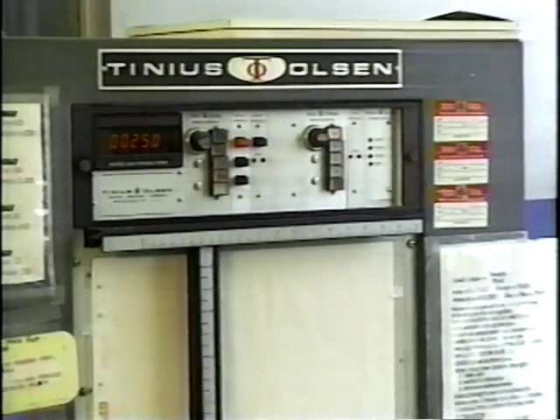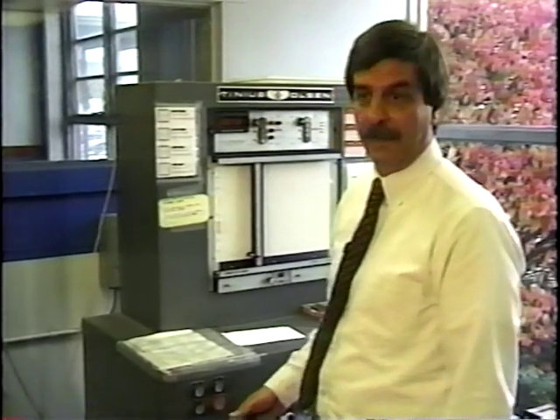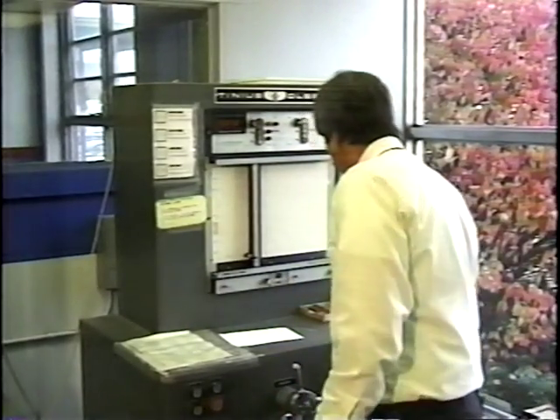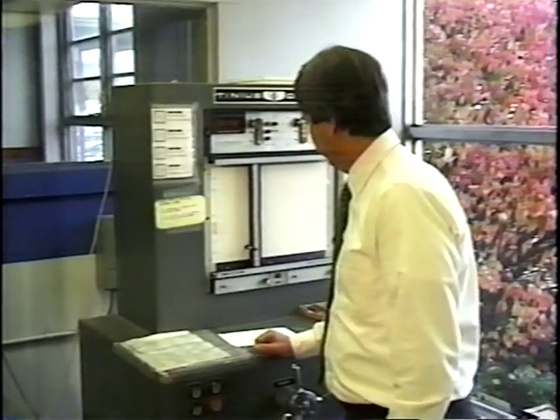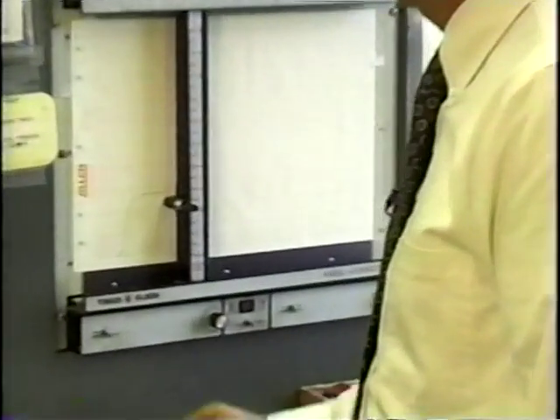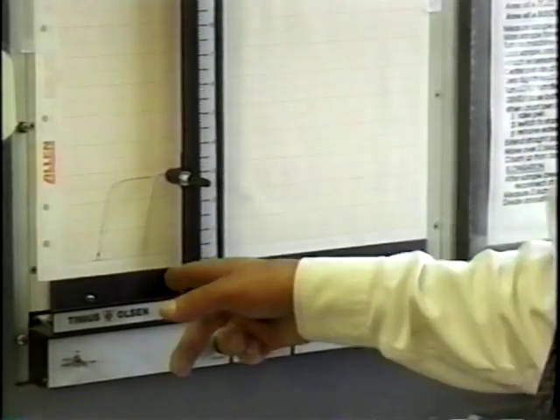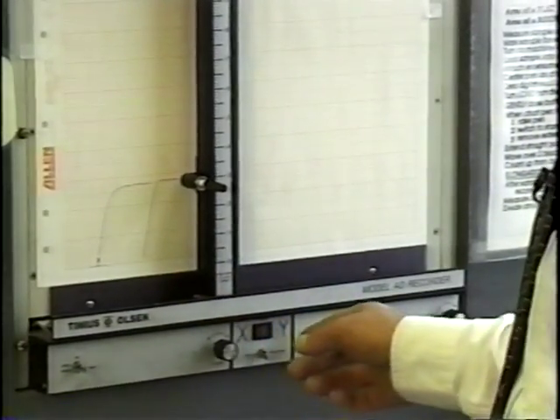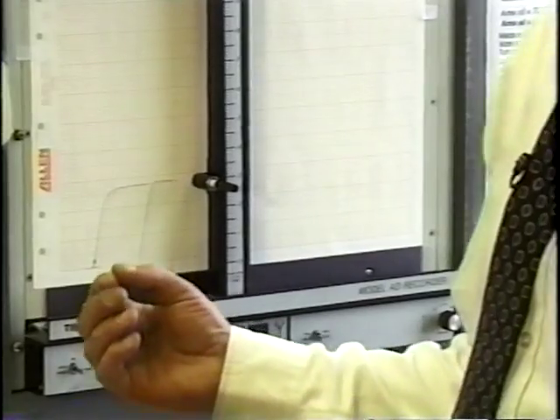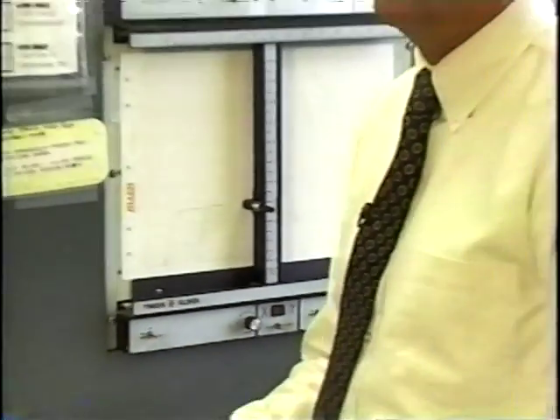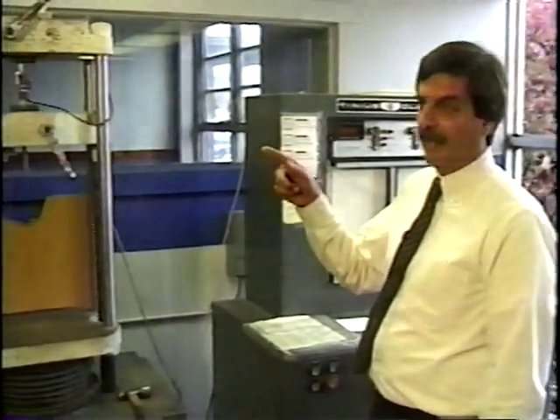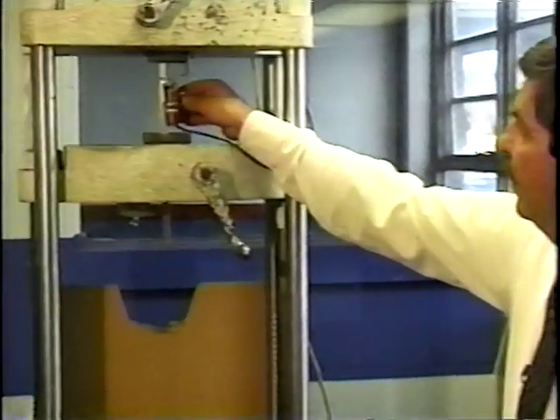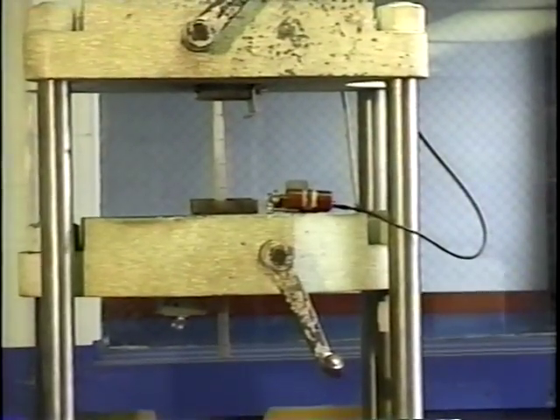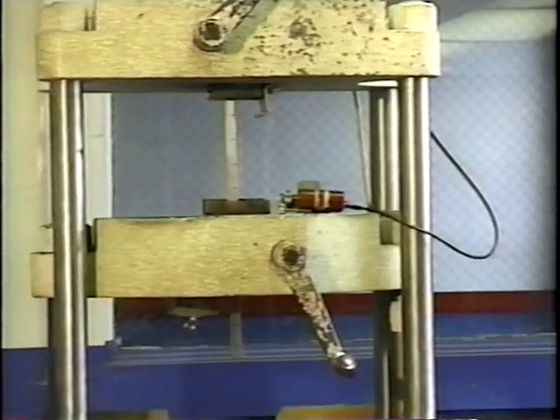Okay, one of the tests that we perform is a tensile test. That determines how strong the material is, when it's going to fail. It's very important to our customers that they know that. What we're doing here is we're plotting the yield strength. It's a stress strain curve, and it's going to tell us when the material reaches a point in its deformation and it won't go back to its original shape. I do have to take the extensometer off so that when the sample does break, we don't damage it in any way. So we do have the stress strain curve.